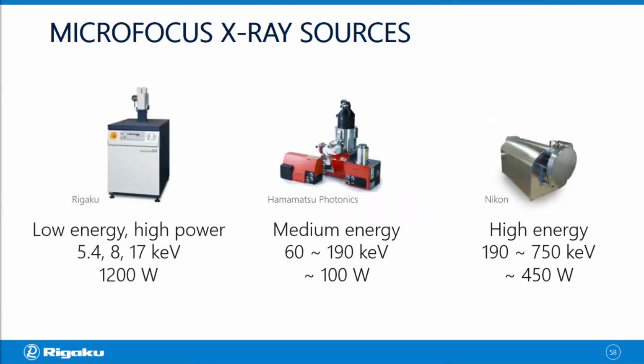This is a rotating anode type X-ray source, and this particular one is Rigaku 007. With this generator X-ray source, you can choose the energy from 5.4, 8, or 17 keV, but you are not compromising on the power because you can operate this one at 1200 watts. And this is a good generator to use for light materials to achieve high contrast and high resolution. So those are the three major categories of X-ray sources.